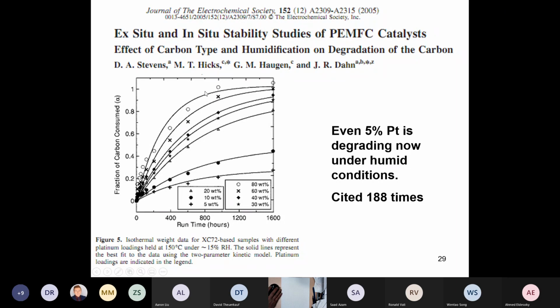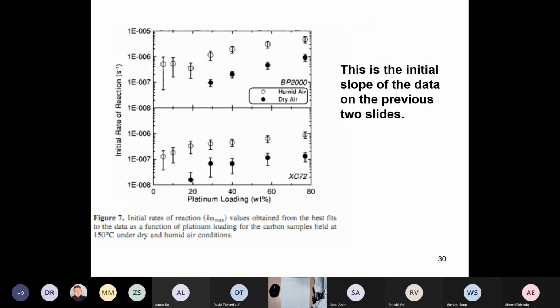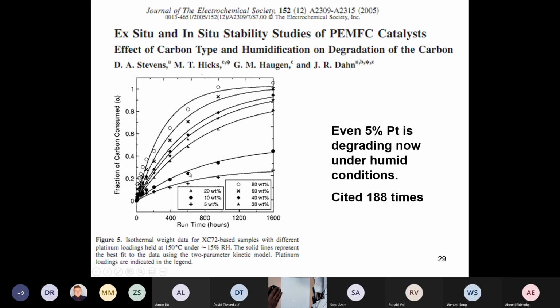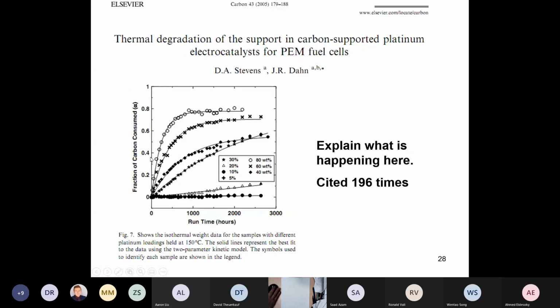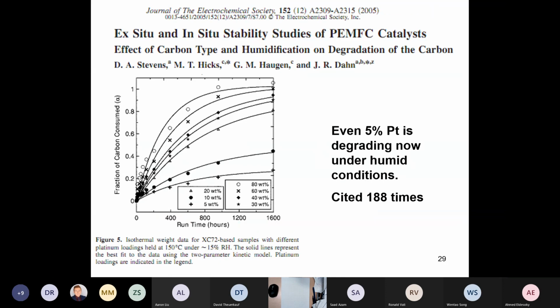They couldn't believe that the carbon was so unstable in the presence of the catalyst, to the production of CO2. It's a very low temperature here. So what's the deal? This slide isn't really too important. It just shows you the initial slope of these curves and these curves, comparing the initial slopes in the dry and humid case.